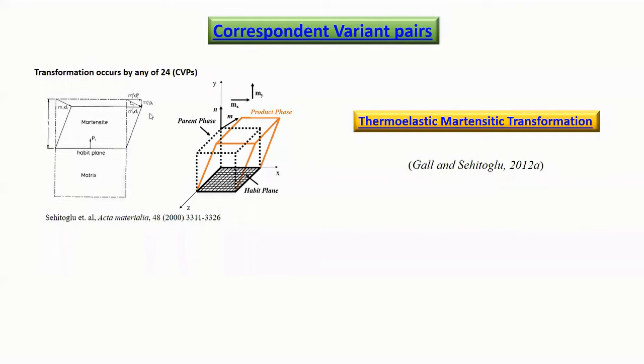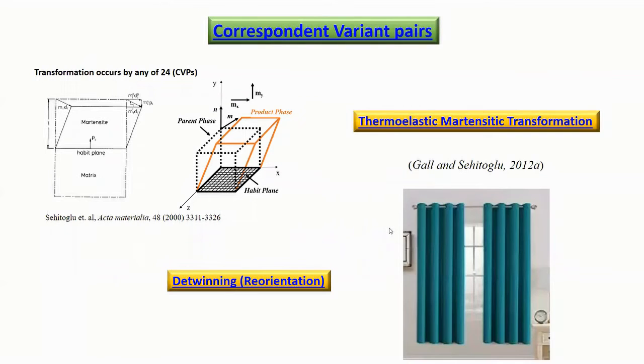And which of these 24 different ways the alloy will choose for the conversion depends on the critical resolved shear stress. Okay, the one that can meet the critical stress for the transformation, it can happen only on that plane. So that is being dictated by the theory, which is called the phenomenological theory of martensitic transformation. You can find the details of all those in these papers, but I thought that this is beyond the scope of this present presentation and have not gone to much details of that.